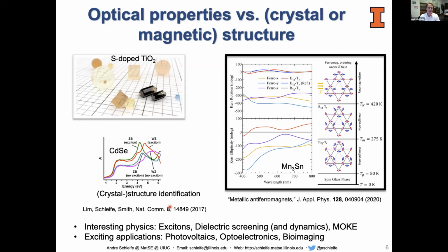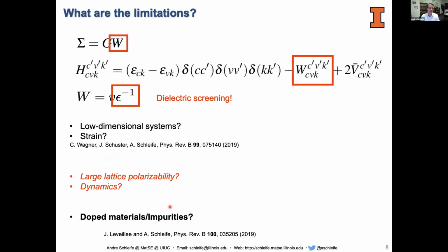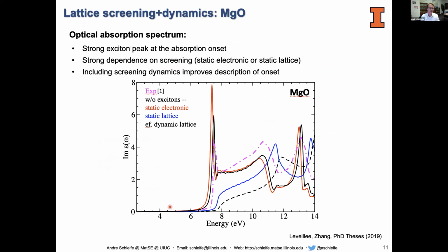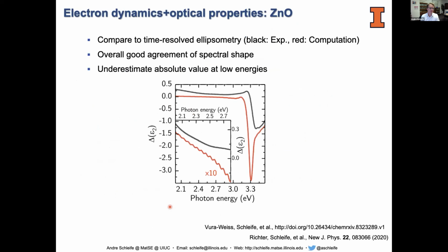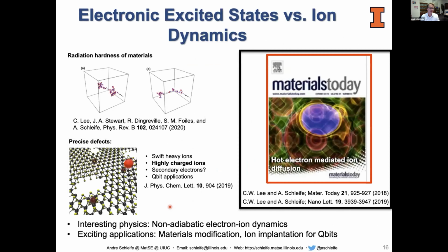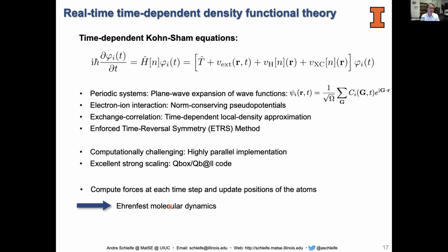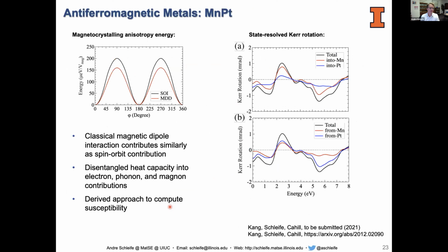Second question was, you talked about manganese platinum, and I didn't understand this anisotropy because manganese platinum is a collinear antiferromagnet, but my recollection is that the moments are aligned in the 1-1-1 plane, and therefore there should be a six-fold anisotropy, where you showed a two-fold anisotropy. So what were you actually presenting?